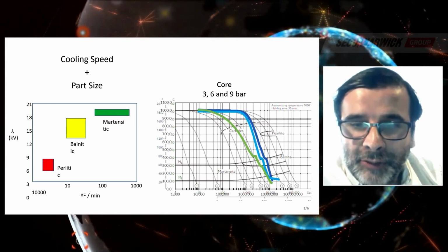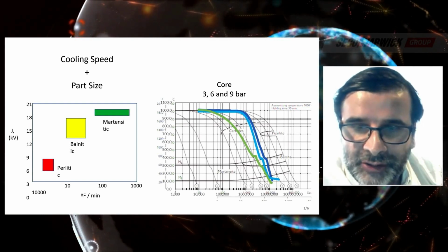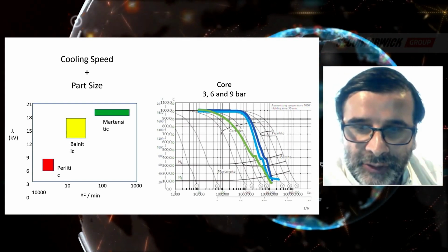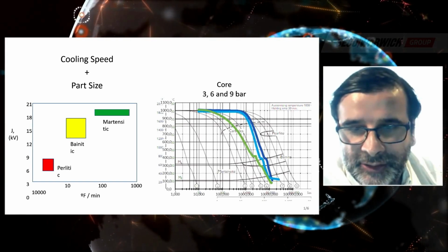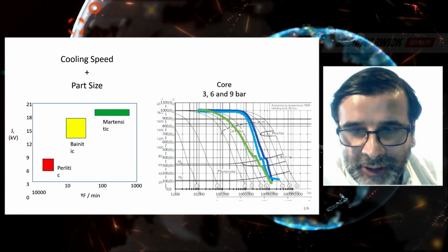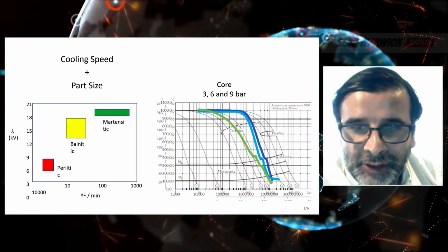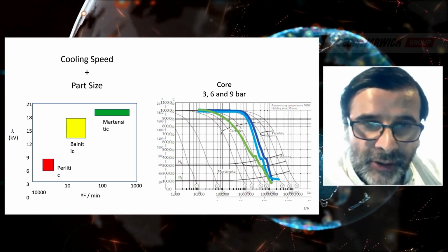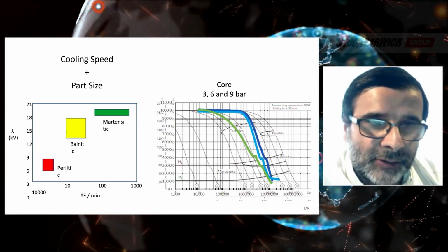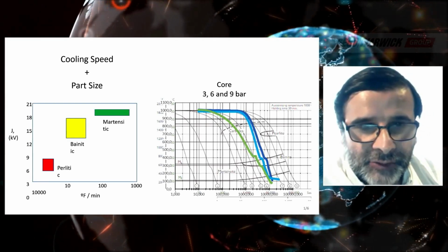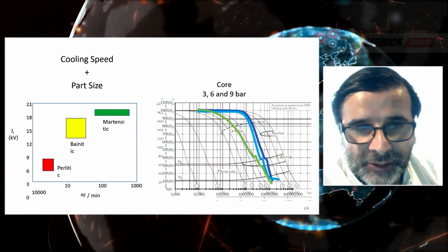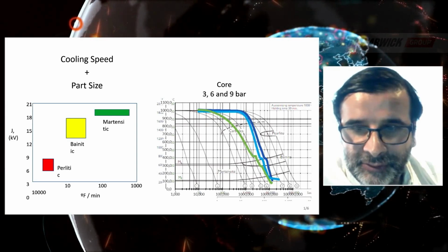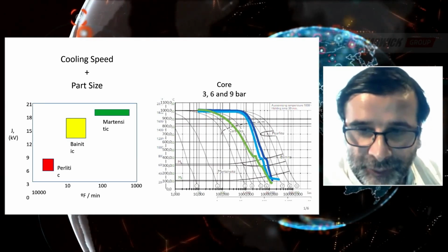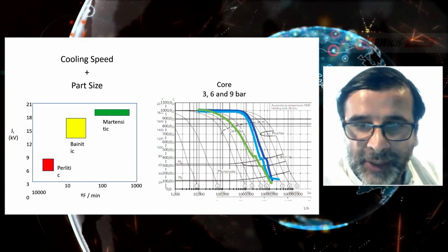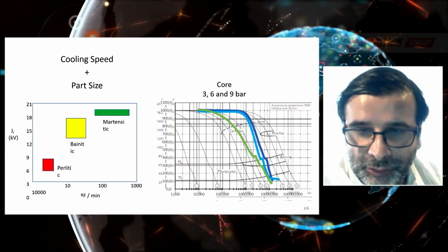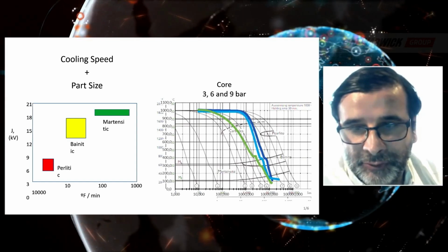So we will achieve a mixed structure. We will not have only martensite at the end of the hardening. We will reach a certain amount of Bainite. This will reduce a little bit the toughness, as we see on the left in this picture. The toughness values will be a little bit lower than expected for small tools cooled fast in vacuum.